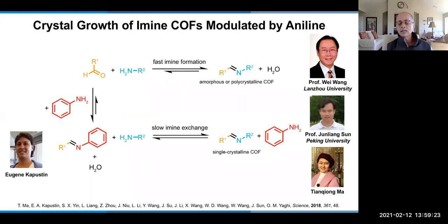The ultimate, of course, is getting those COFs in single crystalline form. And there again, we slow down the exchange reaction with the imine. We do this by adding a competitor to the imine formation. We call it a modulator, which is aniline. Aniline competes in the imine formation reaction and slows down this imine exchange reaction, and therefore we are able to make single crystals of COFs.